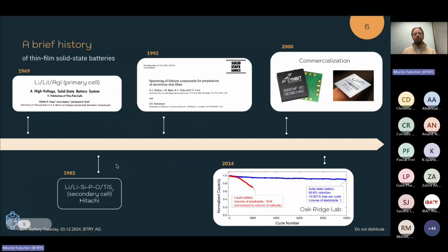In the early 80s, the first secondary rechargeable lithium thin film cell was reported, with titanium disulfide as a cathode and lithium metal as an anode. Then the field really started to take off with the discovery of LiPon as a solid-state electrolyte, which is still the most widely used solid-state electrolyte within thin film batteries. The discovery of LiPon led to the commercialization of many of these thin film batteries, especially in the years 2000 to 2010. There were many companies around the globe who tried to commercialize thin film batteries.